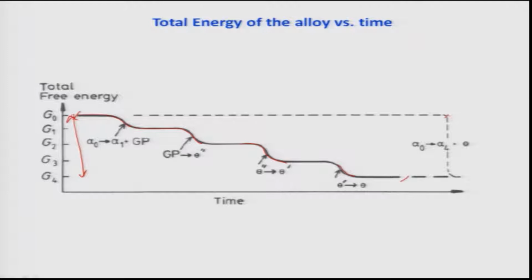On the other hand, as it is shown here, if you want to change alpha 0 to theta directly, the total energy change is very high. Therefore, the system behaves in a logical manner, as I have been telling: it transforms in a sequence from alpha 0 to theta, and we can actually control that. We can stop our heat treatment here,